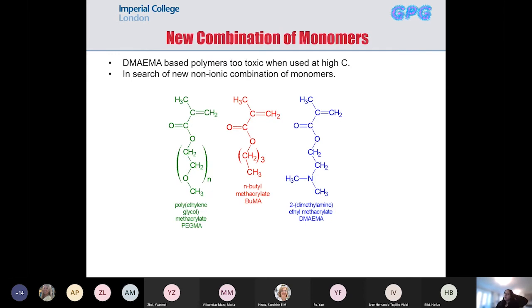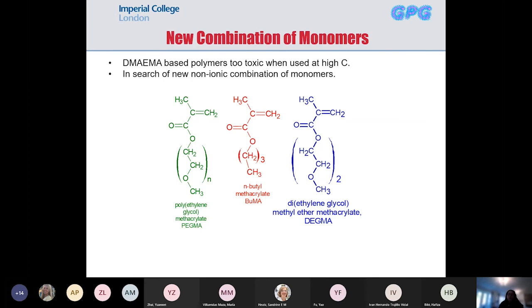So we wanted to move away from the DMAEMA monomer and have monomers now that don't have charges. So we tried a different PEG-based monomer that has less PEG groups. It only has two diethylene glycol groups, and that makes it actually thermoresponsive in the ranges that we wanted to have. So this new combination of monomers was actually patented because nobody has ever done these polymers before, and because we have found that they form gels at much lower concentrations than any polymers that don't contain specific, let's say, peptide groups that we have seen so far.